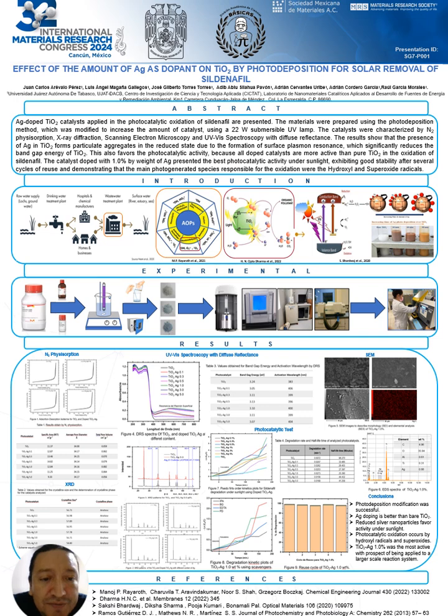As a conclusion, we know that the modification of the photodeposition method was successful. The addition of silver as a dopant improved the photocatalytic properties of the titanium dioxide and enhanced the absorption of light towards the visible region. The sample doped with 1% silver was the most active, showing great stability in its photoreactivity, generating mainly hydroxyl and superoxide radicals to oxidize sildenafil under sunlight.